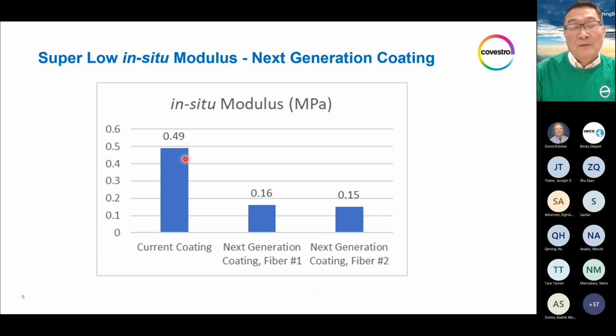The current coating material is about 0.5, so 0.49 megapascal. The next generation coating, primarily for reducing microbending, was reduced to 0.16 or 0.15 megapascal. These two numbers are of the same coating on different fiber samples from a customer trial, and 0.16 and 0.15 are very close. So we're talking about a 70% reduction in in situ modulus. Remember, this is one key point for the highlight: we were able to reduce the in situ modulus by about 70%.